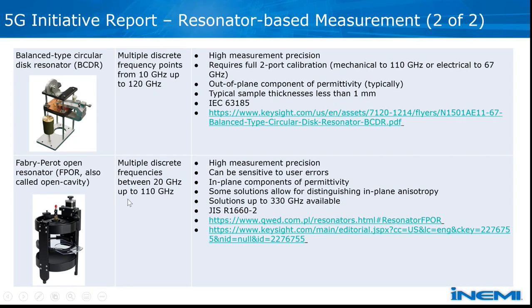The last one, the Fabry-Perot open resonator, is similar to the BCDR in that we get permittivity at multiple discrete frequencies from a single measurement. The solution that we extensively used in further actions was dedicated to measurements from 20 to 110 gigahertz, but commercially available solutions span up to even 330 gigahertz. The Fabry-Perot gives us high precision measurement, but it can be sensitive to user errors. It gives in-plane components of the permittivity, similarly to SPDR and SCR, but some of the solutions allow for distinguishing the in-plane anisotropy of the material if it appears.